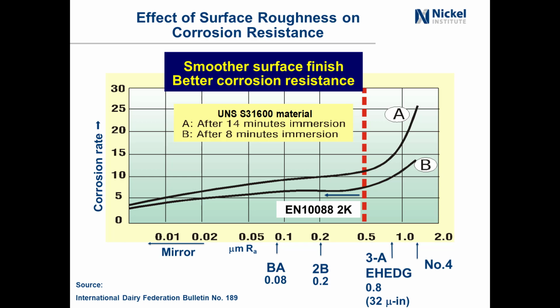And we're looking here where some 316 material was exposed. I don't know what the solution was, because this was an old study. And it was immersed for 8 minutes, which is B, or 14 minutes, which is A. We can see the corrosion rate increases quite slowly until you get to about 0.5 micrometers, and then it starts to increase rapidly after that.